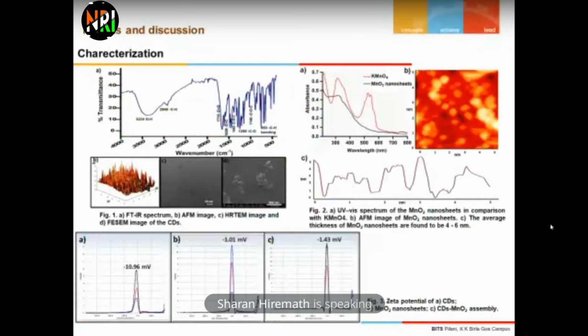With the AFM, we have also seen the size of the particles. There the size of the particles was around 5 to 10 nanometers. It was further confirmed by TEM, where we have got around 5 to 6 nanometers of size for the carbon dots.